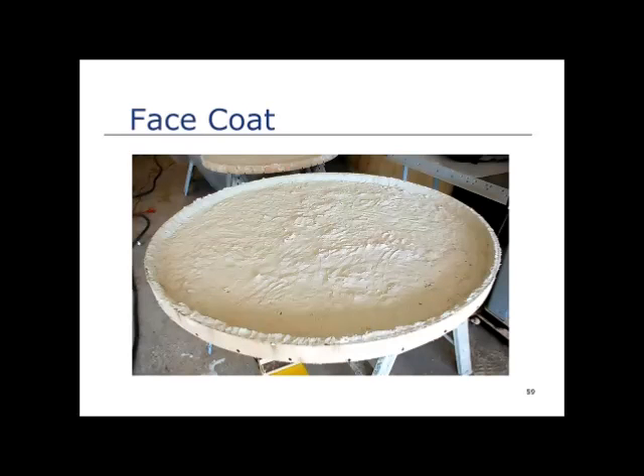With a face coat, because you're putting it on thicker, and this is a cafe table where we've lined what looks like a big pie pan with a big thick crust, it's roughly 3/8 of an inch thick, just hand packed with your hands. So you can't spray that. You make it thicker so it sticks, and then the backer's installed in it. So it's actually easier to do. It's less messy. Spraying your mist coat does make a big mess.